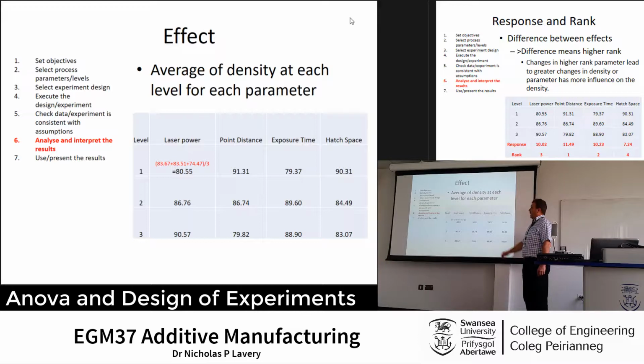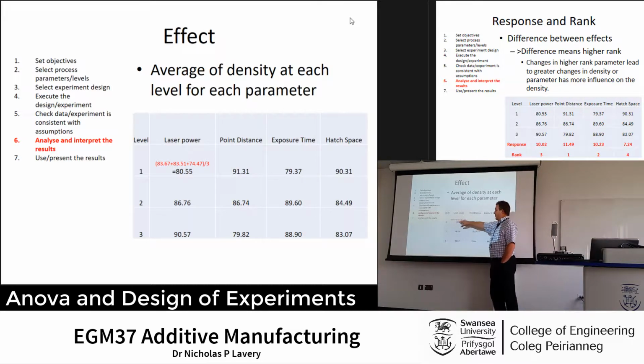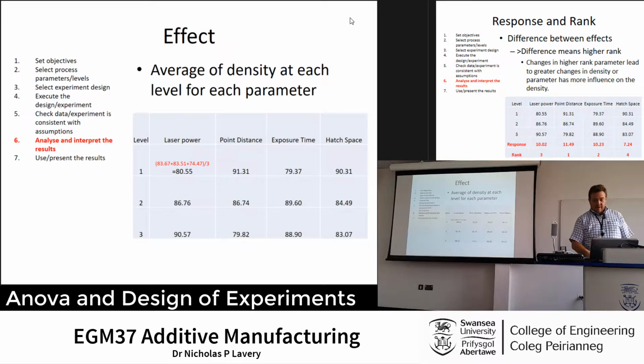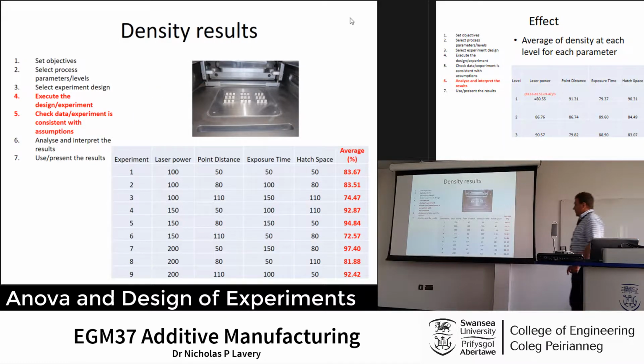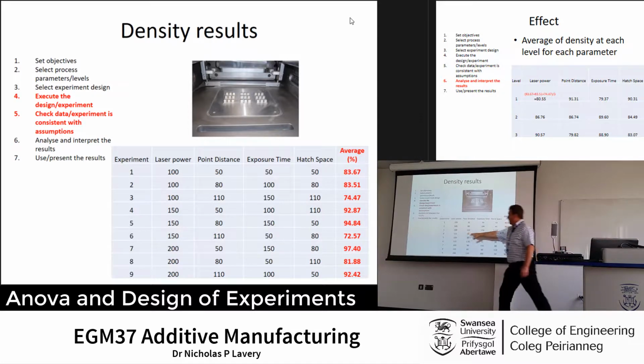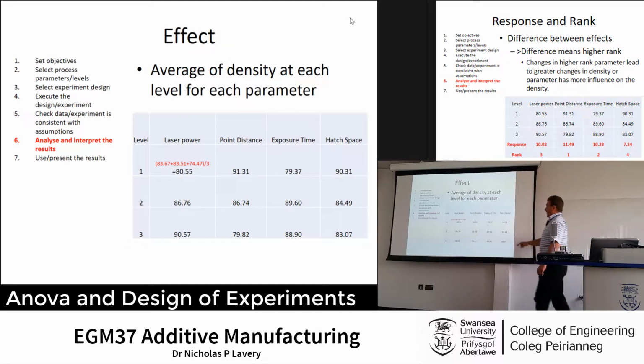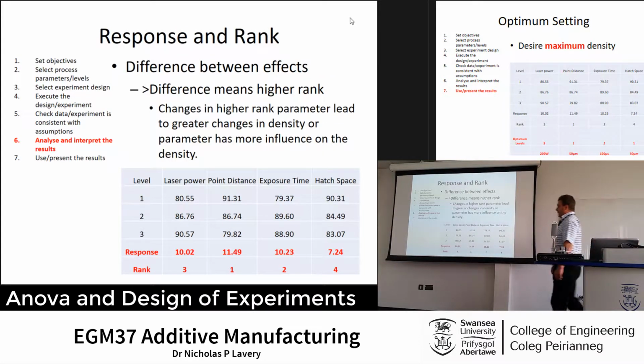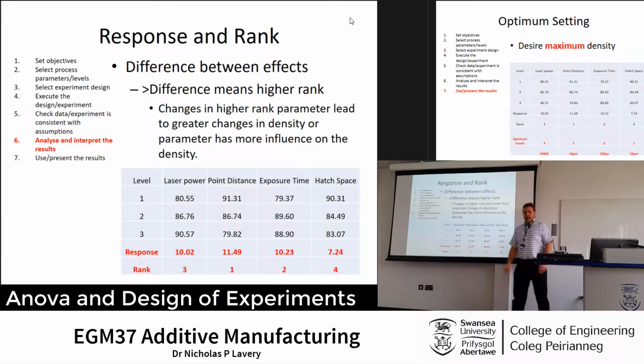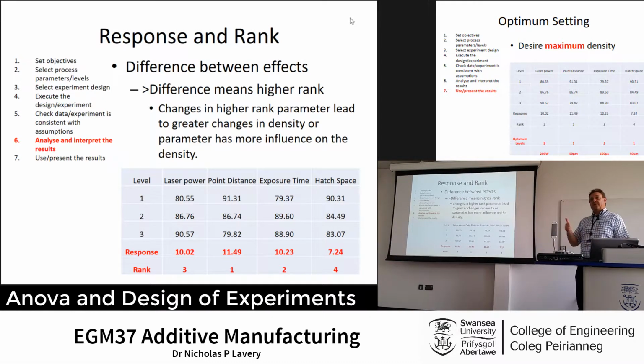What we need to do then, we've got an average of density for each parameter, so we need to work out what the effect is between them. So we'll take the average, 83.67, 83.51. So the average of these 3, where we've kept the P1 fixed, goes into the first part of the effect matrix, and so on. We can populate the rest of them. And that gives us a ranking on the relative importance of each of those parameters over the range of levels that you've set. So in this case, it's telling us, if we assume the results are right, that the point distance is ranked first in terms of importance and the change to the relative density.